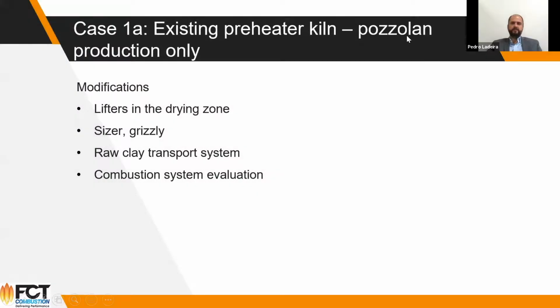So the modification for the pozzolan only is to install the lifters in the drying zone. We have a sizer, we have a grizzly, you have to separate the big chunks in order to convey it to the kiln inlet and feed to the system. Of course, you have to add a raw clay transport system, and our combustion system overall has to be evaluated and adapted for such low temperature burning zone.